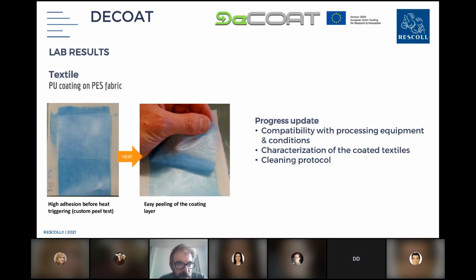Next one is the textile application. So we applied coating on PES fabric, and we got high adhesion before heat triggering. We made for that a custom peel test comparing with the primer and without the primer, and then after heating to 150 degrees C, for this first series of tests, we got easy peeling of the coating layer.